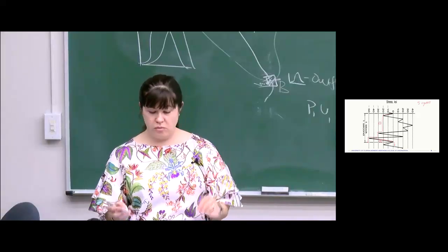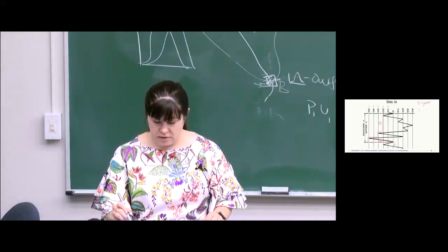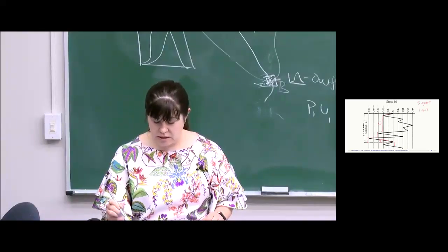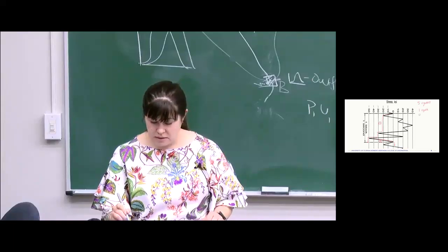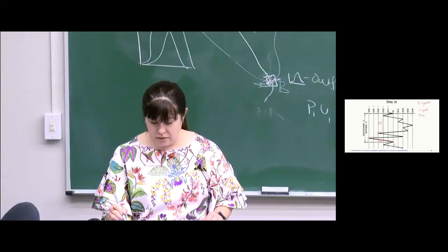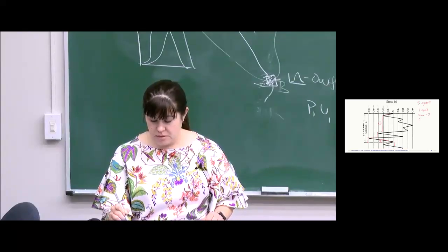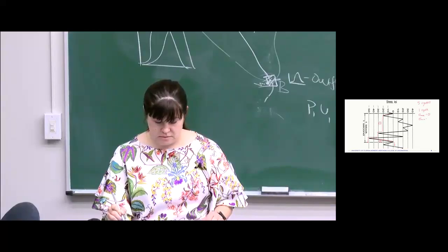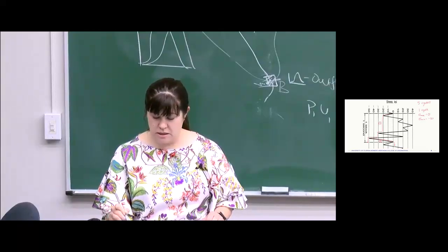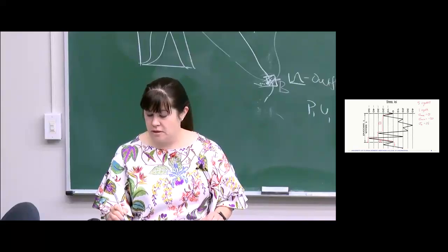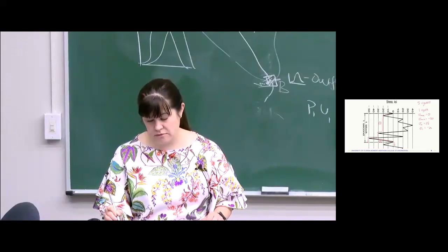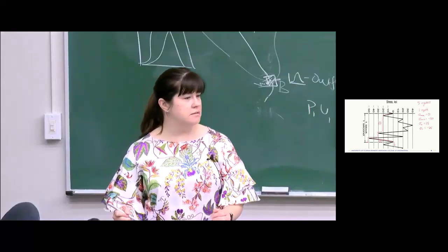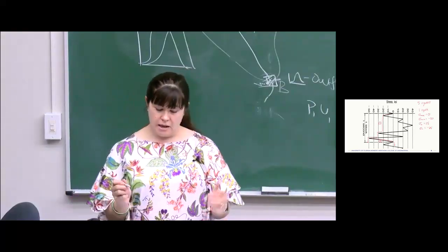So that's considered one cycle, right, with a maximum stress of 0, minimum stress minus 50, which means the amplitude is 25 and mean stress is minus 25. Does that make sense? And so I agree with that.